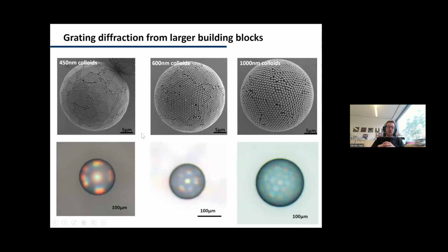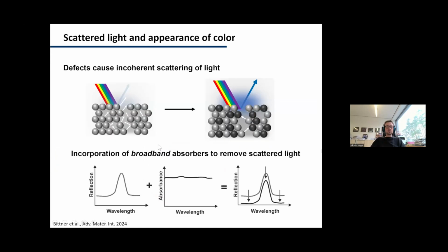But we can also leverage grating diffraction effects if we make the size of the particles larger. And then you see that instead of a single color, we start to see this rainbow-like interference effect on the surface of the particles. And that's a telltale sign of grating diffraction that is manifested in superparticles with larger primary particles. Well, and finally, scattering is always a problem in structural coloration. And the typical way to mitigate this is the incorporation of absorbing materials.